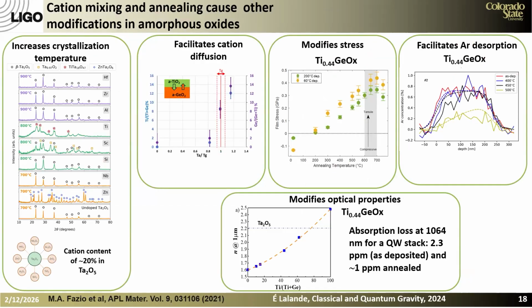We have done a lot of work on alloys. On these alloys, we have shown that alloying also has the benefit of increasing crystallization temperature. We have demonstrated that in Germania, there is cation diffusion. And again, this is important because it allows the atoms to rearrange and form a more favorable network. And we also look at stress in the coatings because ultimately we are going to make multi-layer dielectric coatings.